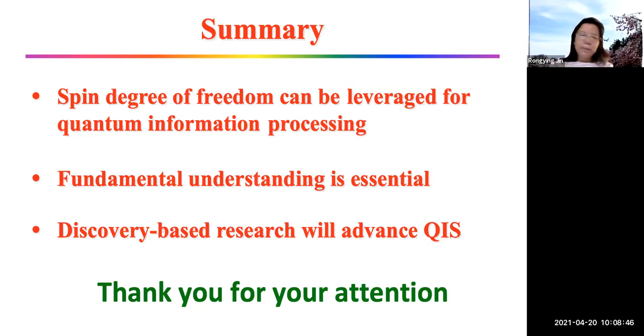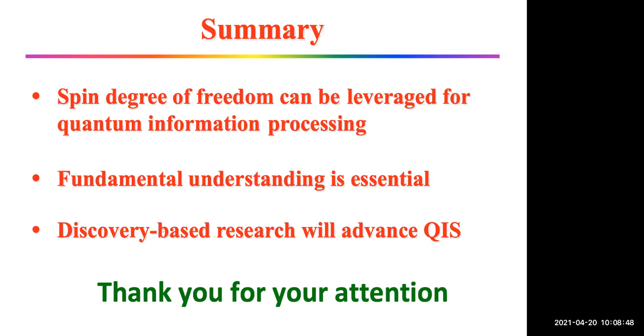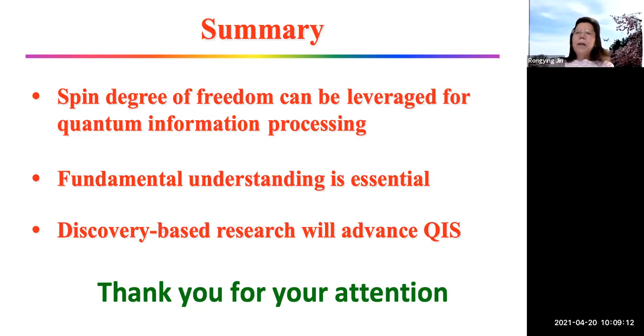Yes, Ilya. What Rongying described is her experiments on the nodes in the bulk. If you're asking about the surface in topological insulators, which is what she showed, we have angle-resolved photoemission data, so you can see directly the dispersion of the peak. When you go to bulk Dirac and Weyl materials, which is what Rongying studies, you need to do more elaborate things. But for topological surfaces, it is as direct as you can get. ARPES directly shows you such a linear Dirac band.